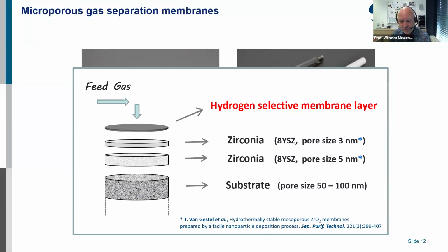So you have the support here. The pore size differs from 50 nanometers up to a few micrometers, depending on where you buy the support. And then, before you make the microporous membrane on top, you need some intermediate layers to decrease the pore size. In the past, gamma aluminium oxide was used, but that is not very stable in humid conditions, and in recent years it was changed to 8YSZ membranes with pore sizes of 5 to 3 nanometers, and these membranes up to here are commercially available currently.